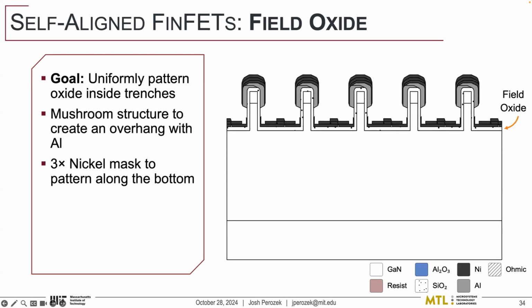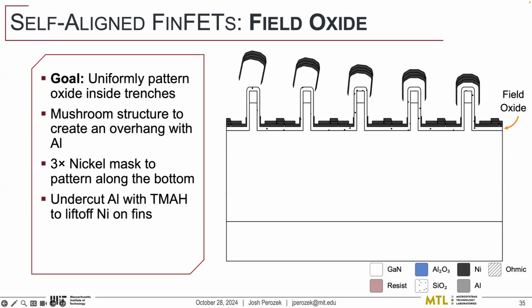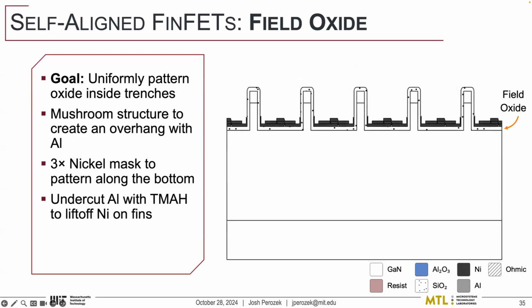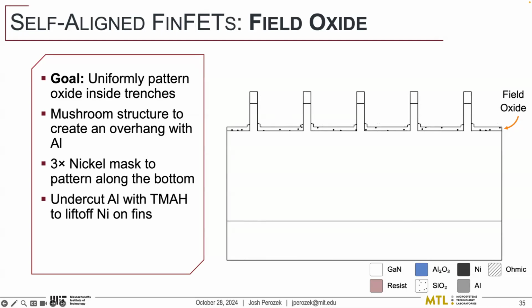we can do the same sidewall structure and pattern that along the base there. We can do 3 different depositions. Ideally, it would be rocking and you could have it uniform, but if you just do 3, you can sufficiently cover the bottom. And what was crucial is that if you use different metals, you can have etch selectivity to them. So we can now undercut that aluminum with even just photoresist developer, TMAH. We'll undercut that. We can lift off the nickel on top of the fins. We're left with just nickel on the bottom. That is now a good mask for etching our silicon dioxide, which we can do with an isotropic dry etch or a wet etch. Then we remove our nickel, and we've got our silicon dioxide at the base of these trenches.